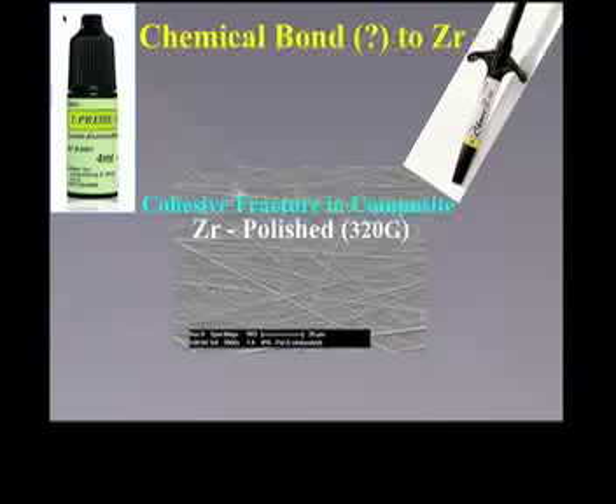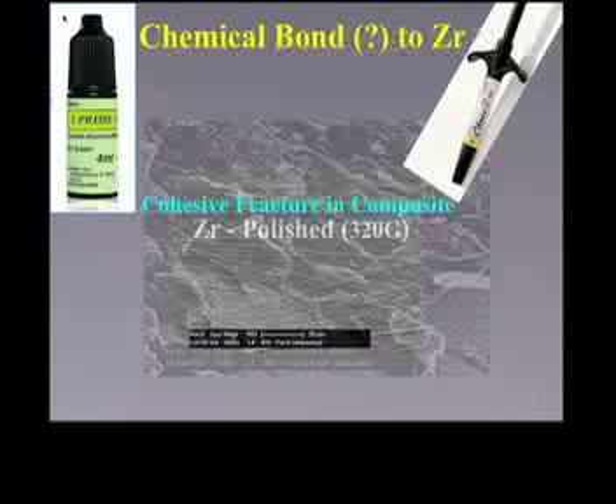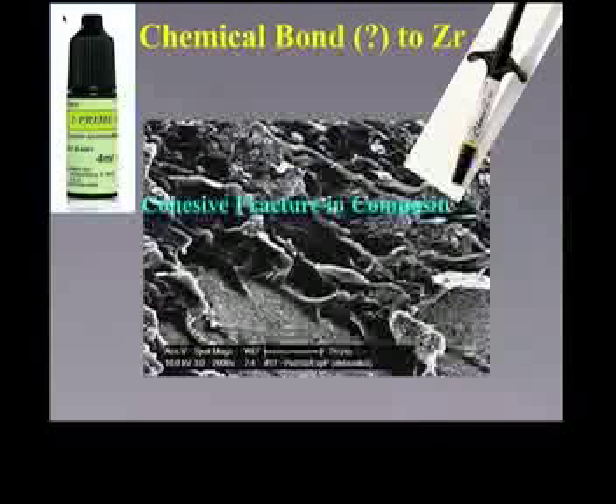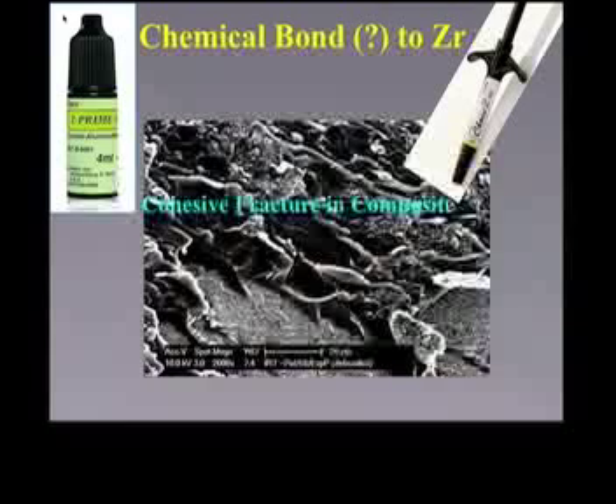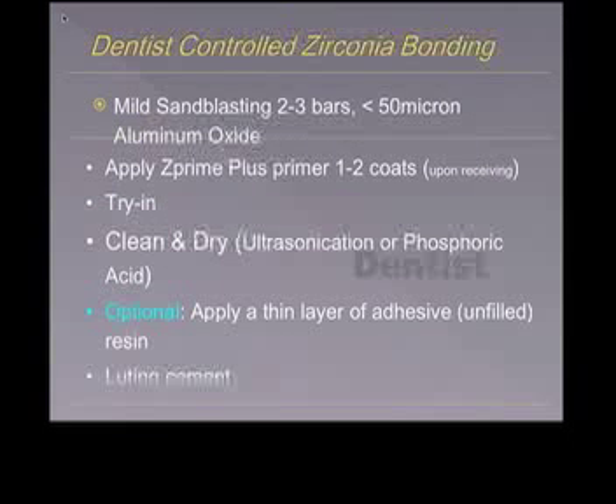Apply the Z-Prime Plus primer, 1 to 2 coats. Try it in, clean and dry. You can apply a thin layer of adhesive luting cement, and it's a very, very easy situation, giving you more confidence and more durability than just typical cements. So definitely take a look at this in your armamentarium in your office.